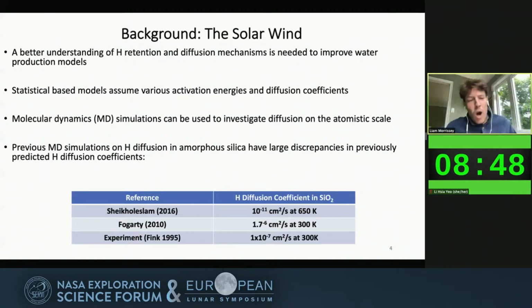Now, in contrast, we can use molecular dynamics, or MD, to actually investigate the diffusion on the atomistic scale. The benefit of this is that when we run these, we're actually simulating the process on the scale in which it's happening. Now, previous MD works on H diffusion in amorphous silica have had a large discrepancy in the previously predicted H diffusion coefficients. So you can see in the table on the bottom, we have a range of orders of magnitude of about 5.